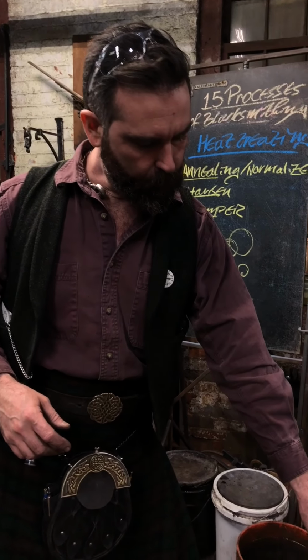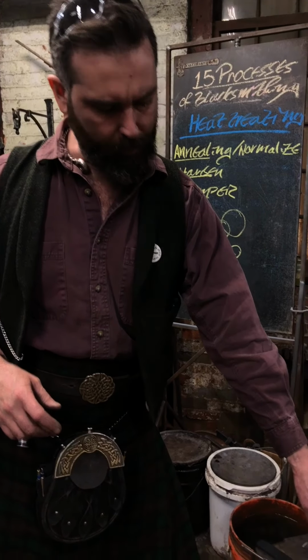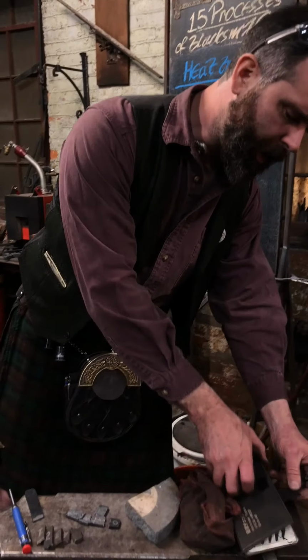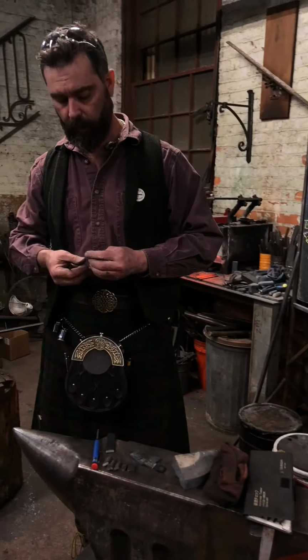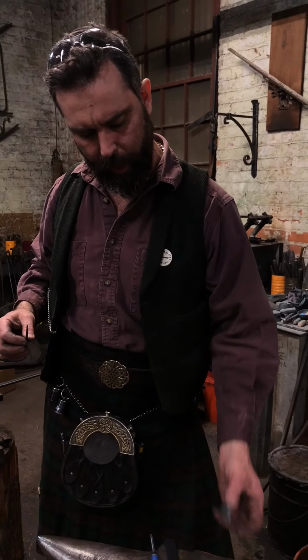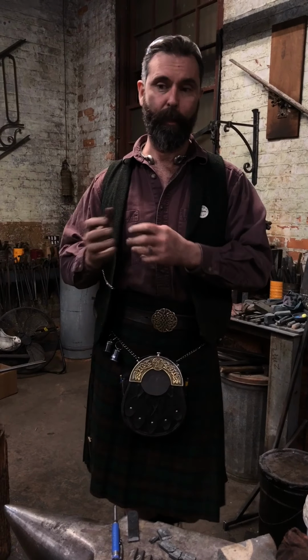So this one being 0, as it were, and this one here being number 4, they are actually the same hardness. And it being O1, I know it's above 65. So I'm getting no cut on that, and I should get no cut on this one as well. Yeah, no cut. But the difference is that the one with the coarse grain structure is hugely more fragile than the one with the fine grain structure. Long and short of it is, if you don't do good normalizing cycles or good normalizing anneals to bring your grain structure down, your tool, knife, whatever it might be, will not be at the best of its capabilities.